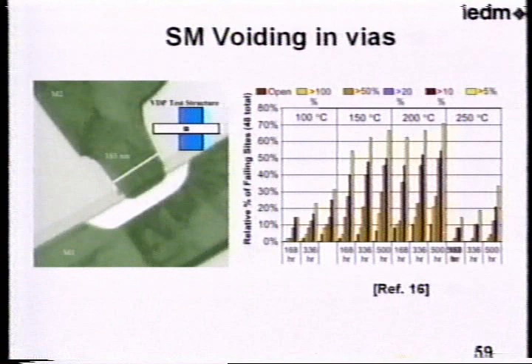And also there is another mode of stress migration. In that case, the void was formed at the upper side of the interconnect, like this. And this kind of stress migration voiding in vias is strongly dependent on temperature. They are maximum at around 150 or 200 degrees C.